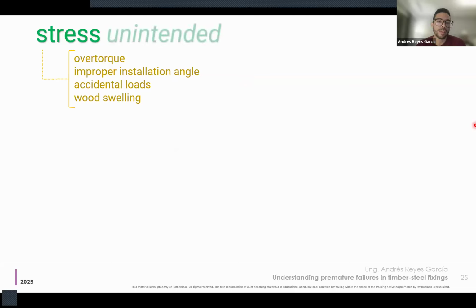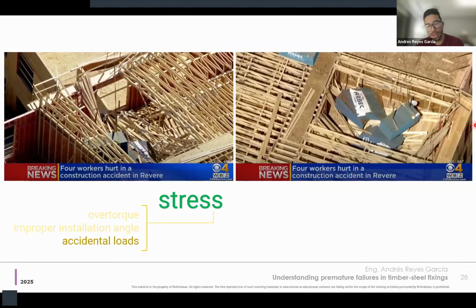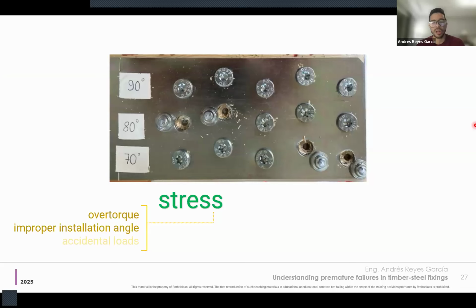By stressors I mean unintended stressors, some stress that the designer cannot or didn't include in the design. It can be some accidental load. This didn't happen to us. This is just an example I found on the internet when looking for accidental loads in wood construction. Transport can be an important factor there. But also over torque and improper installation angle. This is a campaign that we did in dry conditions, inserting the screws at max speed in thick metal plates at different angles, for example here at 80 degrees, 70 degrees. So we know that can break a screw.